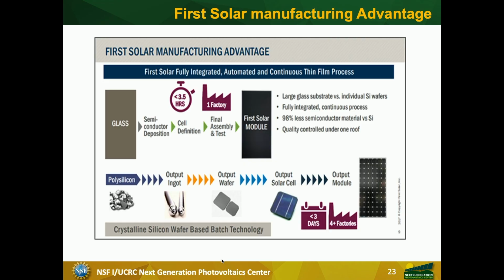And we define the cell by laser scribing, because you can't have a single cell that will be low voltage and high current. Here you want higher voltages and acceptable current. So you do the cell definition, and then a polymer is glued at the back and gets sealed and put together, and then we get a module. It takes about 3.5 hours to go from glass to a module in a line where there are about 10 people on the line. It's coming to the vision, right? And there are very few people. It's going continuous in line, with nearly consistent production.